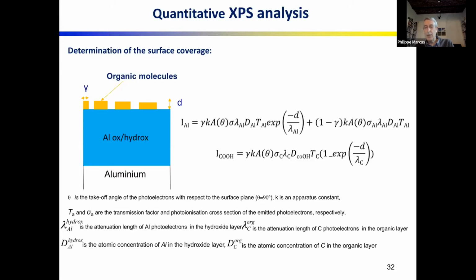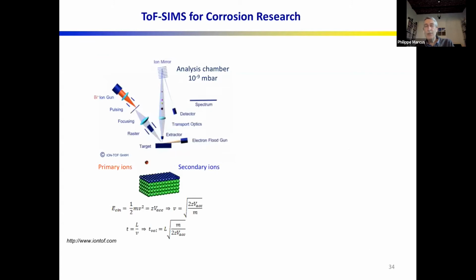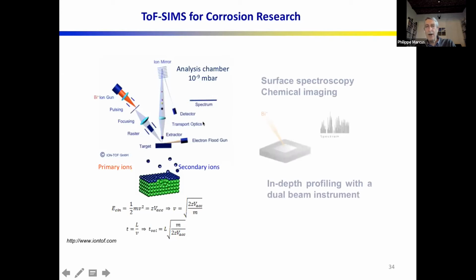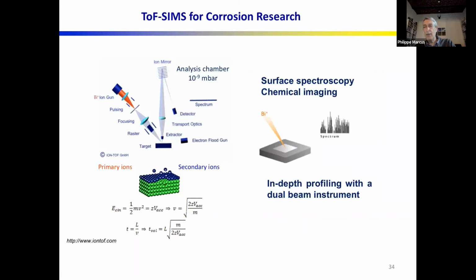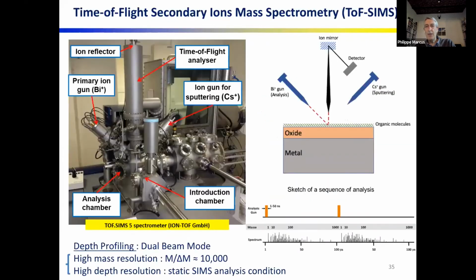highly efficient technique. We also use time of flight SIMS, which in general for corrosion research, and in particular here for looking at corrosion inhibitors. And this is the principle. Here we have a beam of primary ions that are hitting the surface. Secondary ions are emitted and analyzed, and this analysis provides a mass spectrum in which we can detect all the masses and all the elements at the surface. We can combine this with a second beam to make in-depth profiles. And this is the equipment that we are using in my lab.